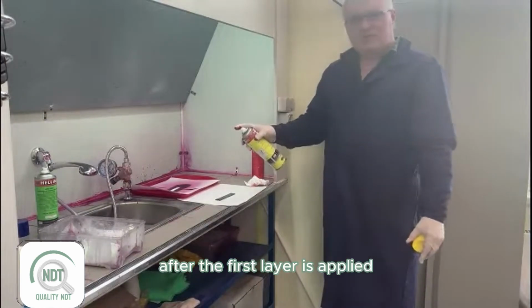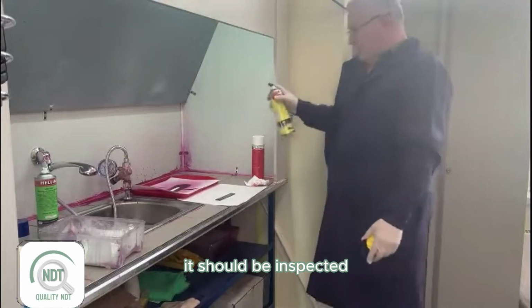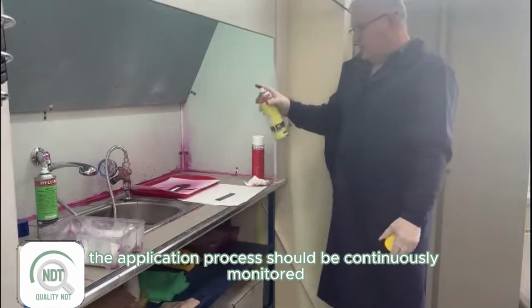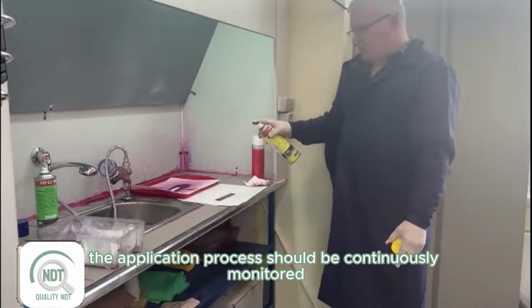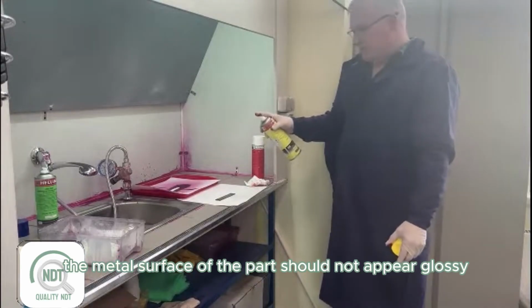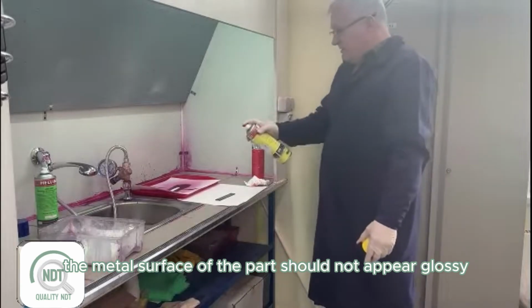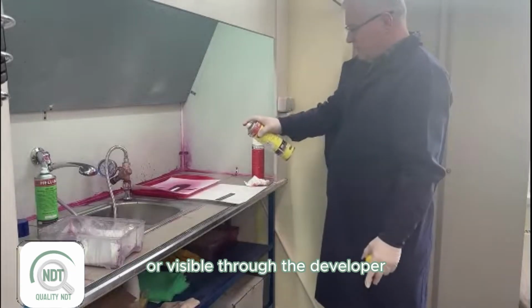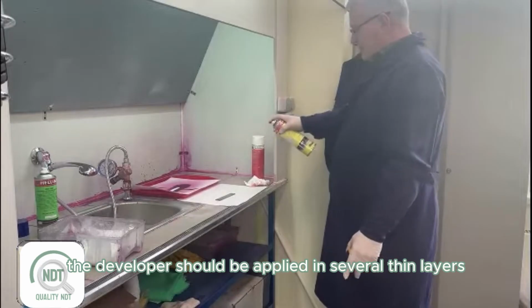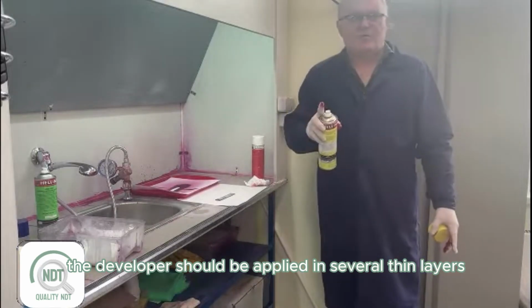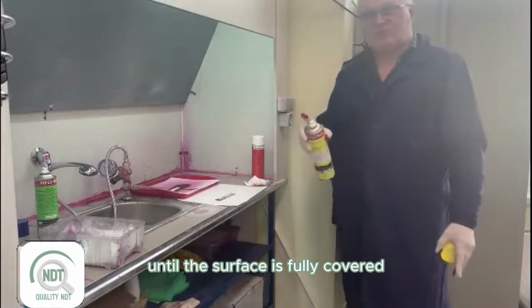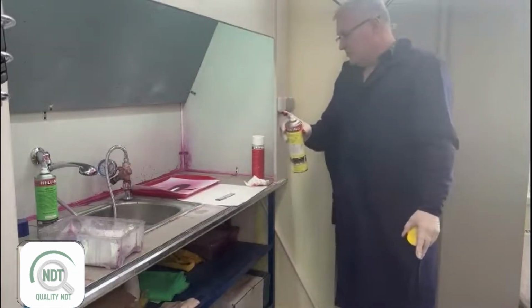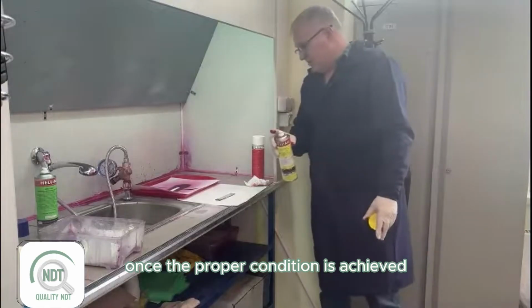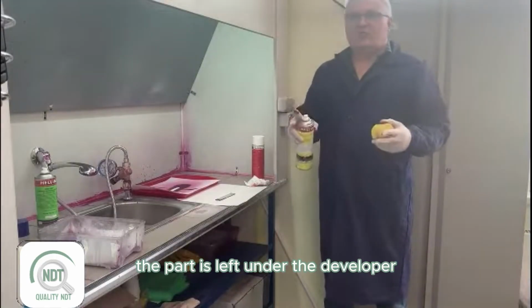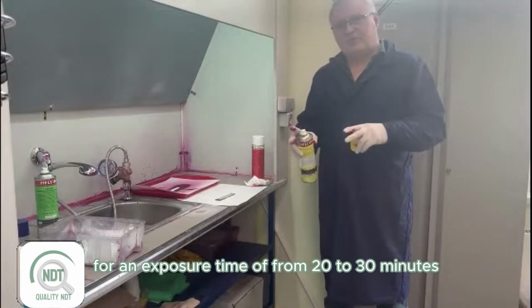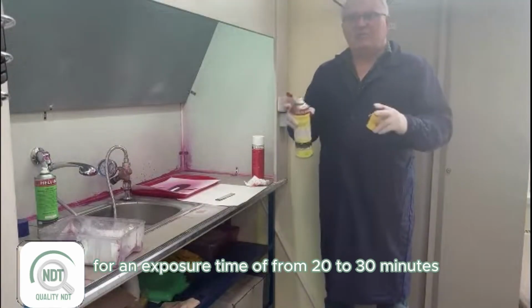After the first layer is applied, it should be inspected. The application process should be continuously monitored. The metal surface of the part should not appear glossy or visible through the developer. The developer should be applied in several thin layers until the surface is fully covered. Once the proper condition is achieved, the part is left under the developer for an exposure time of from 20 to 30 minutes.